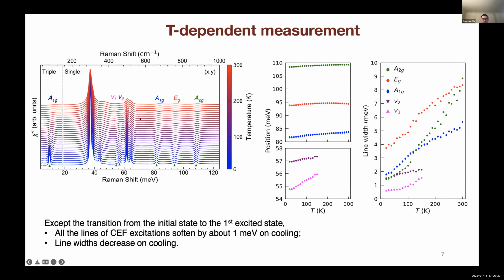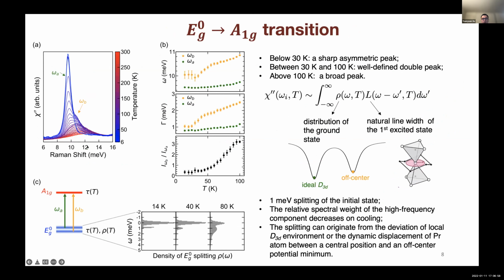Next, I'm showing the temperature dependence of the Raman spectra. The crystal field excitations are marked by the green triangles, and the right figure shows the evolution of the positions and line widths as a function of temperature, except the transition from the ground state to the first excited state. We see all the peaks of crystal field excitations soften by about 1 meV, and the line width of the peaks decreases on cooling. But if we zoom in on the low frequency range and probe the transition from the ground state doublet to the first excited state, we can see a sharp asymmetric peak below 30 Kelvin, and between 30 and 100 Kelvin, we can find a double peak.